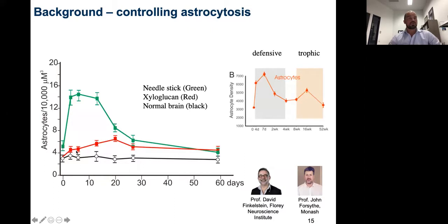And basically what we found was we saw a suppression, I suppose, of this inflammatory response. And we didn't know why for years, but actually what we determined was that it was due to a sugar moiety on that hydrogel, which was suppressing the inflammation. And basically it was doing this through inhibiting the Rho-ROCK signaling pathway within the astrocytes. So on the cell, there's all these receptors that respond to different proteins, and it was actually inhibiting a certain pathway within the cell, which was then resulting in that cytoskeletal change from that reactive state back to that cytotrophic phenotype.